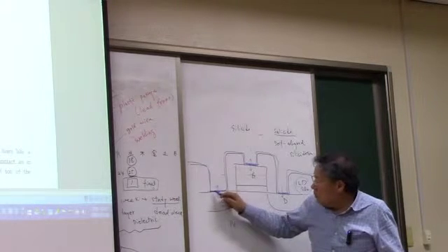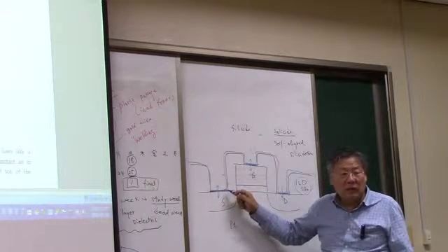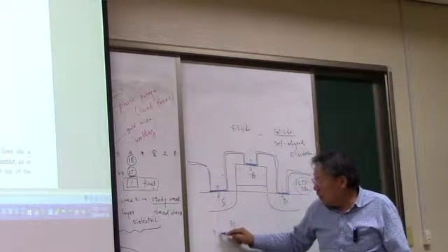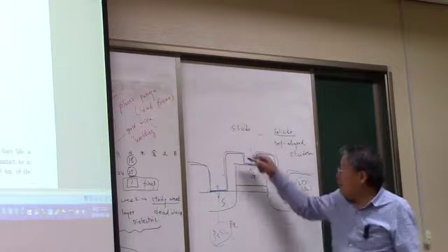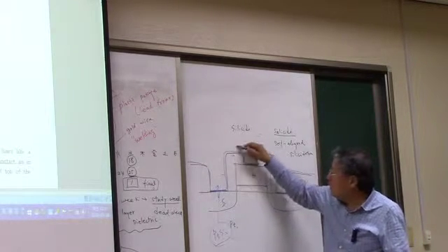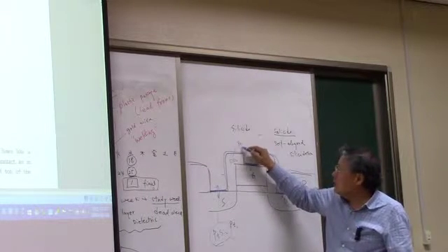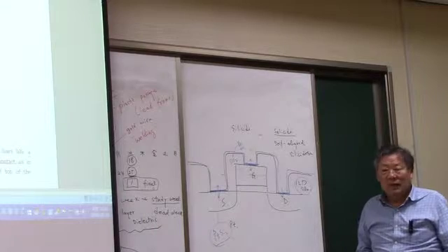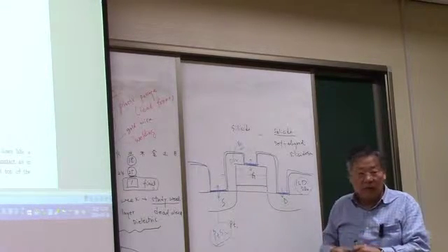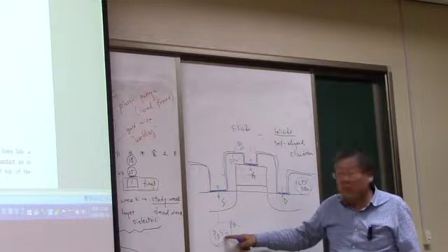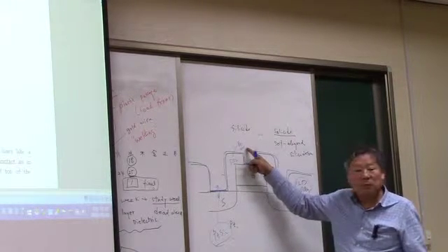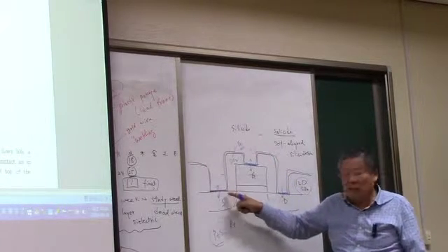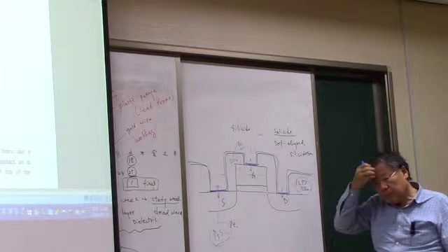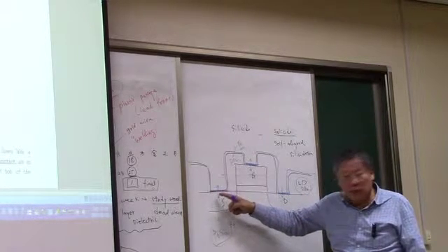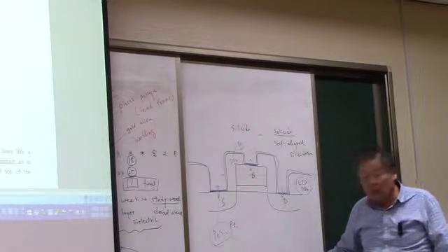Then the platinum sitting on top of this silicon is going to form the platinum silicide, okay? And the platinum on top of this silicon oxide just remains as platinum, like that. So if you put this in the wet etchant, then this platinum silicide is not going to be etched. Only this platinum is going to be etched, so that it has a self-aligned silicide. In other words, only the contact holes are going to form a silicide, okay?